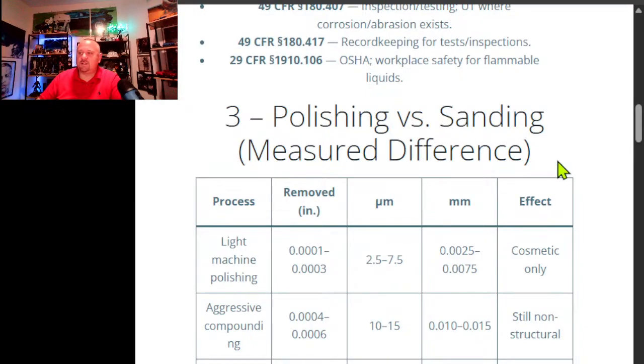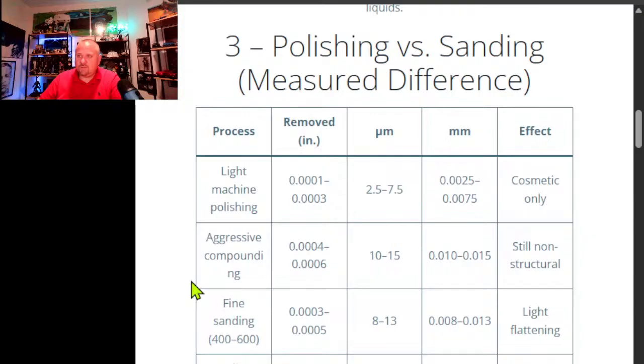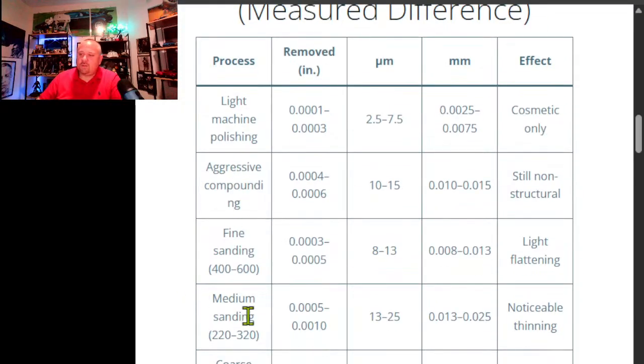So, polishing versus sanding difference. These are actual measurements that have been scientifically taken. Light machine polishing for what we do could take off 0.0025 to 0.0075. It's cosmetic only. Even with our aggressive compounding, which is the most aggressive that we do, it is still 0.010 to 0.015. It's non-structural. We're not doing anything to the structure of the metal, where there is no structural change.